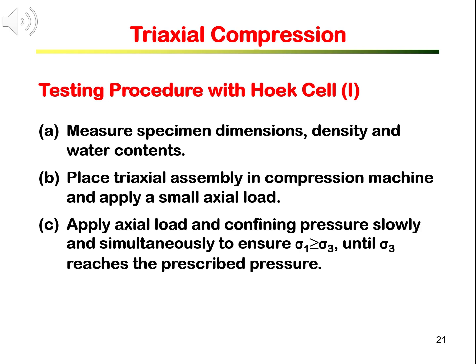We first apply a small axial load to the specimen assembly. This is to fix the triaxial assembly in place and keep it from moving around while pressurizing the triaxial cell. Then we apply axial load and the confining pressure slowly and simultaneously to ensure axial stress is always slightly higher than confining pressure, until confining pressure reaches the prescribed pressure value.